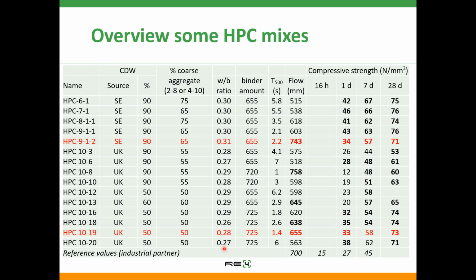The previous slide showed a few examples of self-compacting concrete. We also ran screening tests for high-performance concrete mixes. Here you see the same properties that CREAG wants this mix to achieve. But you also see something happening, depending on the CDW source, the one we call SE. In that one, we succeeded in replacing 90% of the aggregates while fulfilling the properties CREAG requested. When changing to another CDW, which we shortened UK, we only succeeded in replacing 50% and fulfilling the requirements.